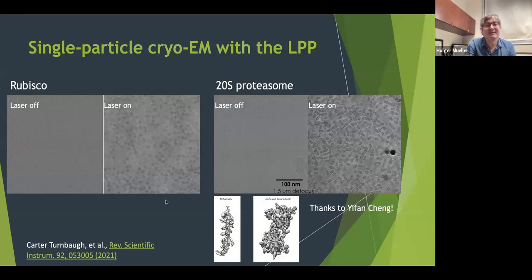Yes, we can. On the left-hand side, you see Rubisco, and on the right-hand side, you see 20S proteasome. By the way, Yifan Cheng was very nice in making specimens for us. Thank you, Yifan, in case you're here. On the left-hand side, you see images without the laser operating. On the right, you see a different spot of the same grid with the laser on. Both panels use the same defocus, same exposure, and so on. And you can see the contrast enhancement caused by the laser phase plate quite clearly.